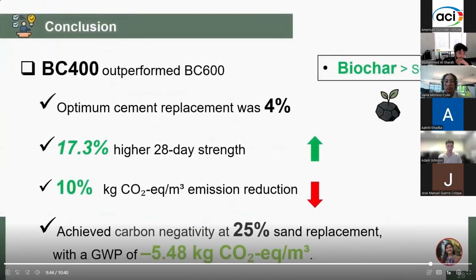So, to conclude, this study highlights that BC 400 outperformed BC 600 in both strength and sustainability. At just 4% cement replacement, a 17% increase in compressive strength was achieved, along with the 10% carbon dioxide emission reduction, which is a significant result. Even with sand replacement, at 25% replacement, we were able to achieve a carbon negative mortar with minus 5.48 kg carbon dioxide equivalent reduction, which is remarkable considering the minor compromise in strength.